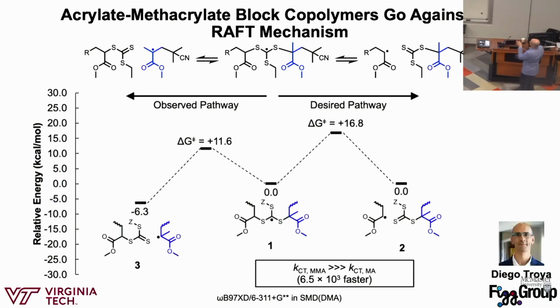So we did DFT calculations just to show this more tangibly. So this is still that middle chain transfer process. So this is where we're going to start in the energy diagram. So we have this radical. What we want to do is fragment off to get this PMA radical. We can see that the thermodynamics are relatively thermoneutral, and then we have this energy barrier of 16.8 kcal per mole. But if we compare that to the other pathway of just fragmenting off this methyl methacrylate fragment, we see a lower energy barrier, and it's also more thermodynamically favorable because of this tertiary radical.